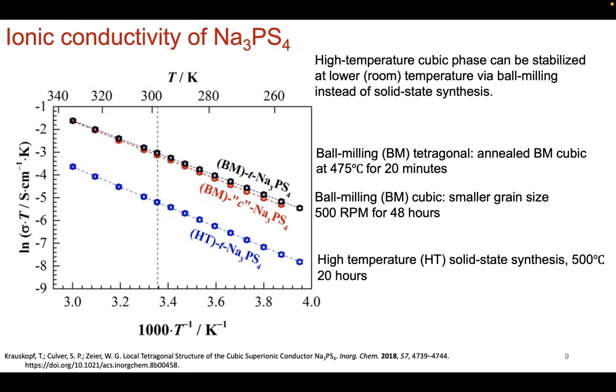So this study, looking at the ion conductivity of Na3PS4, what you could see is if you do conventional solid state synthesis, you put in Na2S, you put in P2S5, and maybe a little sprinkling of phosphorus, a little sprinkling of sulfur, you get your Na3PS4. You'll get the tetragonal phase because that's the low temperature phase that will be stabilized at room temperature. Now, if you ball mill instead of doing solid state synthesis, denoted as BM here, you can access the cubic phase, but at lower temperatures.